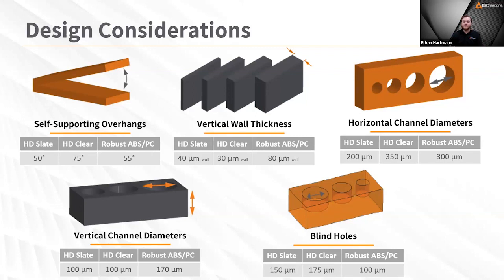The vertical wall thickness is when there are freestanding walls, various thicknesses, all of the same height. The failure criteria for these was when the wall either didn't print at all, due to it being such a small feature, or when the wall started flaking off during the printing process. You pull it off, you'd see the wall kind of formed, it was breaking.